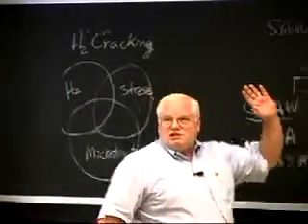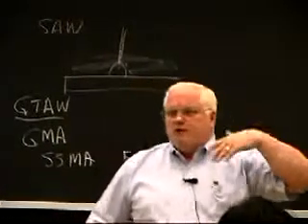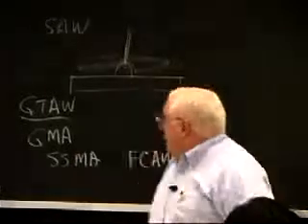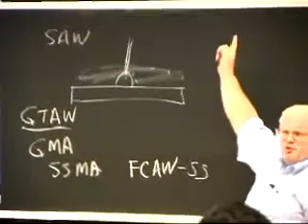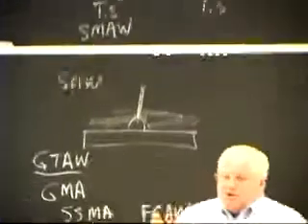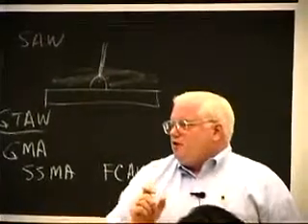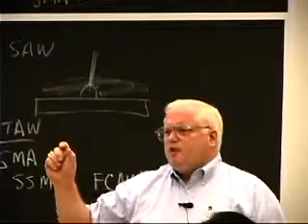So we can use a 6010 electrode on 36 KSI yield steel, which is A36 garden variety building or bridge steel. I have a 60 KSI tensile strength, and I think the minimum is 52 KSI yield strength on that 6011 electrode. And that means that the welding electrode on 6011 is actually substantially stronger than the 36 KSI yield strength or 40-some KSI tensile strength.